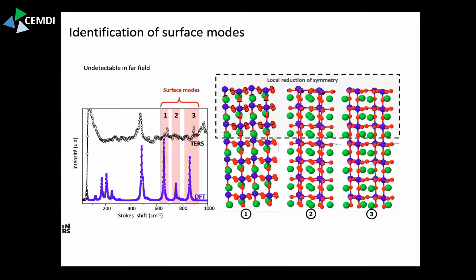So this is the part where things got really exciting for us. We were for the first time able to calculate surface modes. Everything down here should be perfectly Raman silent due to the continuous translational symmetry. But if we look at these modes on the surface, which by the way also get damped to the inside, we see that there are some modes that actually lack inversion symmetry. The surface is by definition breaking inversion symmetry. And so we have these different modes, and they correspond to peaks that we actually do observe.